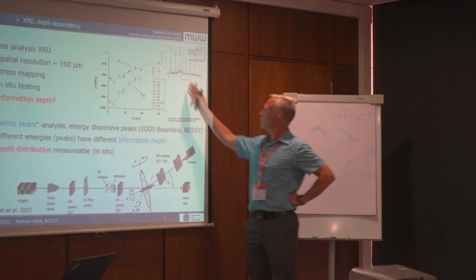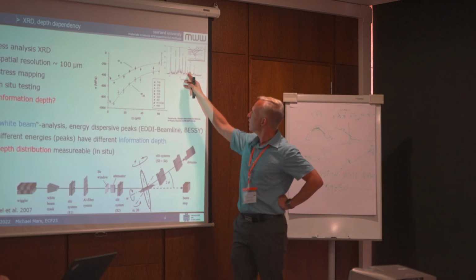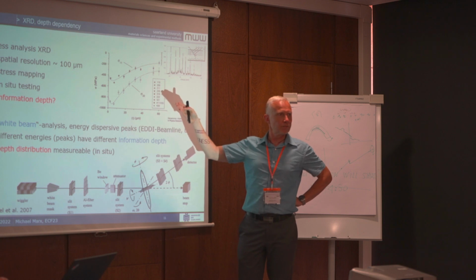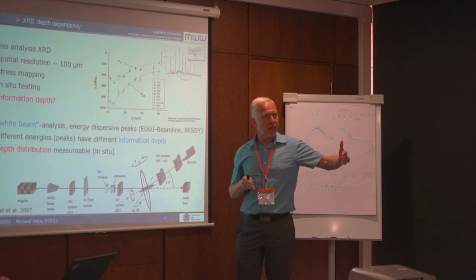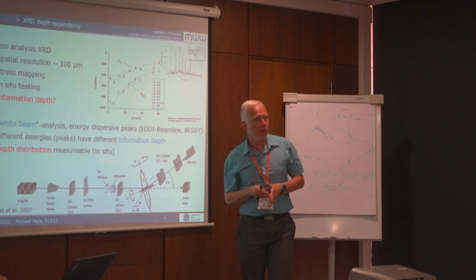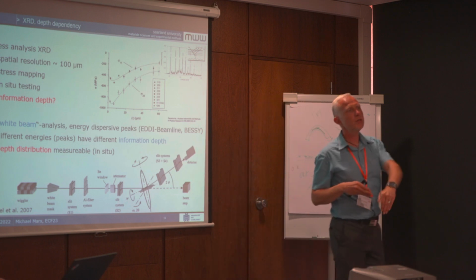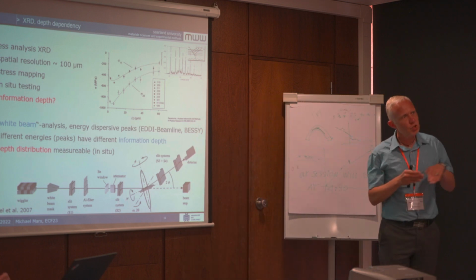But in this case, sure, you also get for this peak some information collected from the outer areas, because these X-rays are going completely through the specimen, but just to these steps.